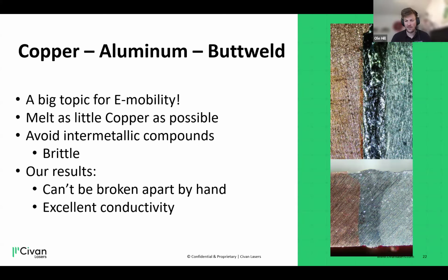It will never have the strength of a copper to copper weld or aluminum to aluminum weld. I would be very surprised to see that happening. But our results, let's say, you cannot break it apart by hand. I will also have a nice video showing you that it is indeed quite durable. And what we could measure recently was excellent conductivity.